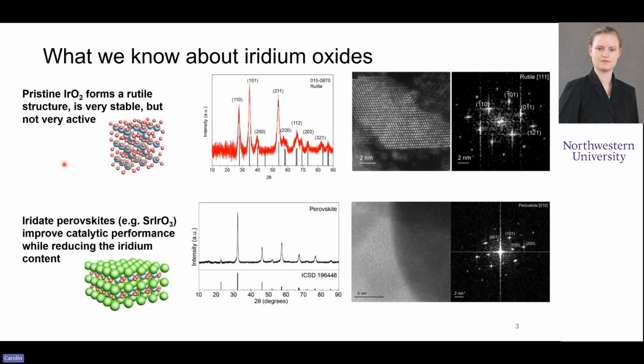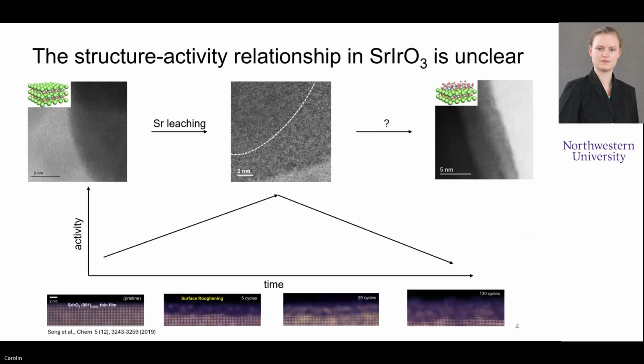One of the class of materials that's been studied quite a bit are these iridate perovskites, such as the strontium iridate, for example, because these tend to be more active for oxygen evolution. But at the same time, they reduce the amount of iridium that's present in the catalyst. And so there's been a number of studies on these iridate perovskites. But what's interesting about them is that we don't know fully why they are as good at water splitting as they are. And so when we look at this strontium iridate perovskite, the pristine material is fully crystalline.